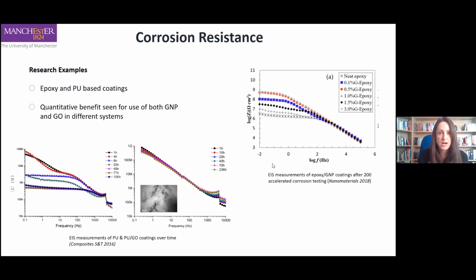The other graph on the right, again, we're looking at impedance modulus in a Bode plot, measured for an epoxy graphene composite coating with different loadings of graphene. And this is just graphene nanoplatelets. It's not GO, and it's been loaded with 0.1 to 3% by weight of GNP. The coatings have been subjected to salt spray testing for 200 hours before they've been measured.